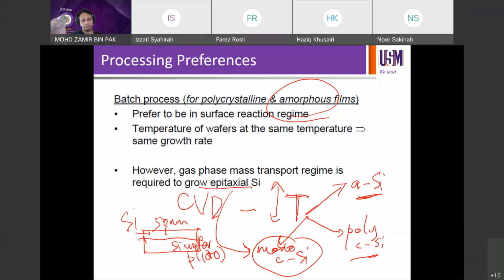And the crystallinity of the deposited layer, in this case, this layer, will take up the crystallinity of the substrate. Maknanya dia akan follow the crystallinity of your silicon wafer. In this case, P100 is monocrystalline. So as a result, the epi layer, the deposited layer here, by CVD at high temperature, will emulate or will follow the crystallinity of the substrate, which is monocrystalline. So as a result, you can get 15 nanometer of monocrystalline silicon, right? So that can be done. So it's just about how do you regulate the temperature. So if you go for high temperature, it's a lot easier to get monocrystal whatever on whatever. So monocrystal silicon on silicon in this case.